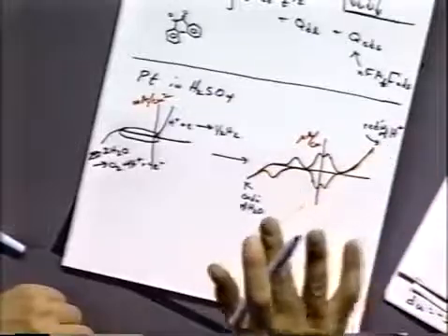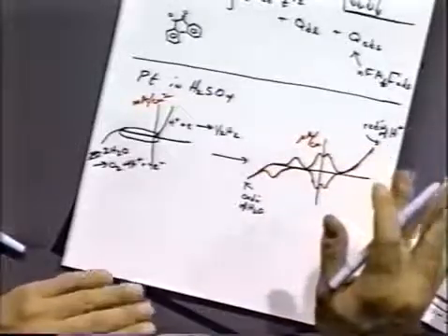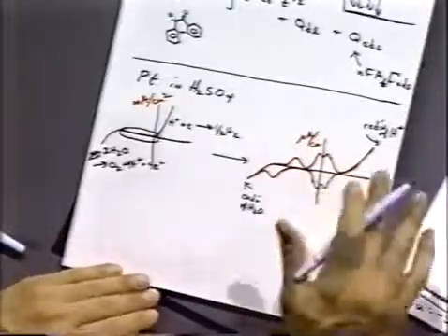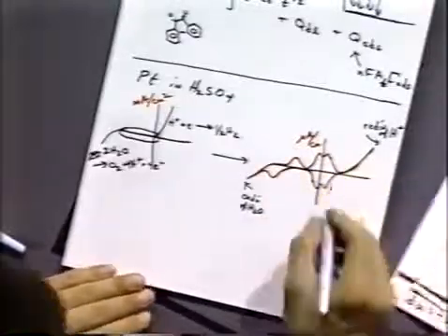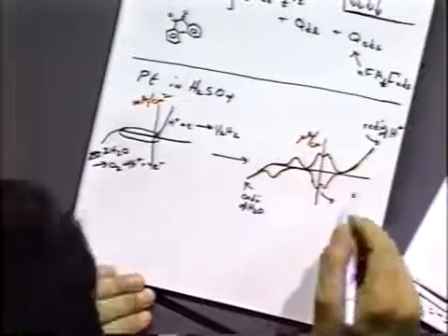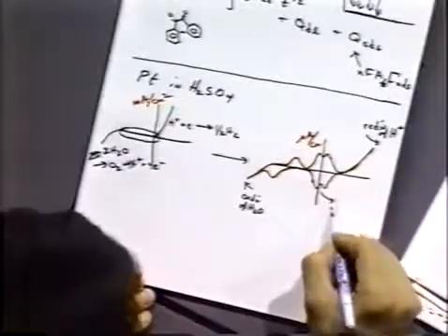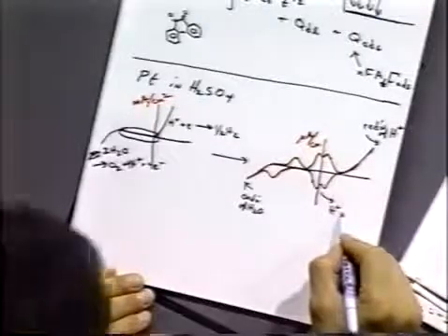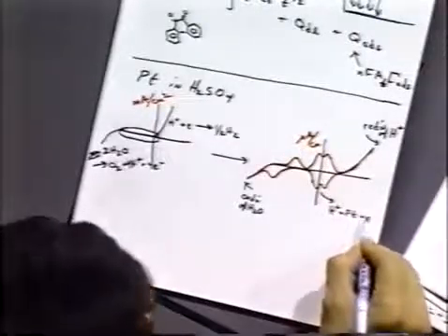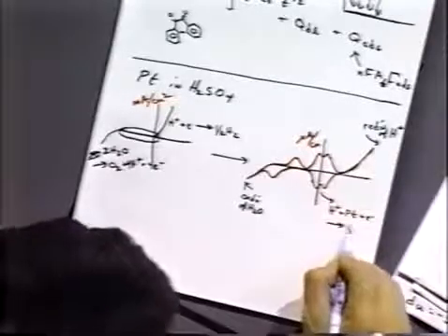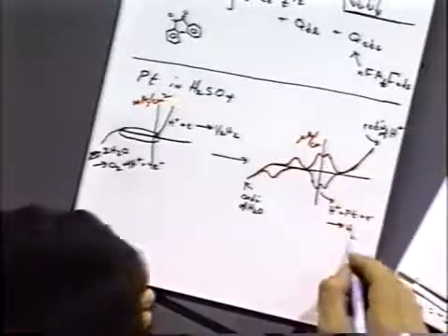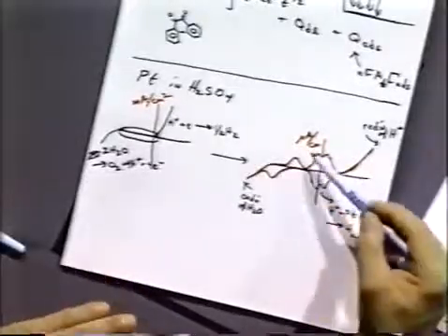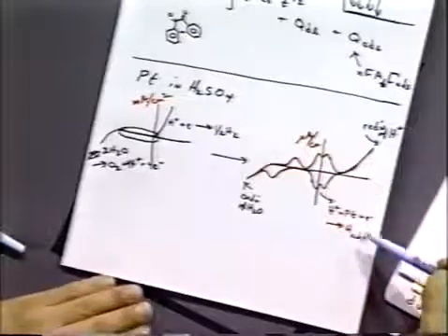The hydrogen ions actually adsorb quite strongly on the platinum. There's a monolayer coverage of these hydrogen atoms on the ions on the surface of the platinum. And so what you find is that you take the hydrogen ions and in the presence of platinum and 1 electron, you form a monolayer of adsorbed hydrogen atoms. And so that's what you're seeing here is the reduction to form adsorbed hydrogen atoms.